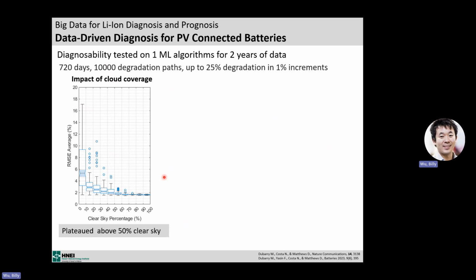Now calculate in your head, 20% degradation in a decade, how much degradation is that per day? It's 0.00 something. So you don't need to do it every day. And certainly don't do it every second. Like you see some papers with cloud, I want to diagnose every second. The claim of a degradation model has to be 0.00000 something percent, which is completely unrealistic and unnecessary. Anyway, going back to the topic, we see that with 50% or more clear sky, it works great.